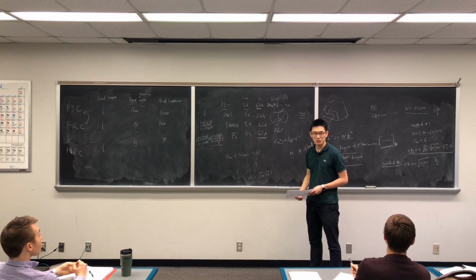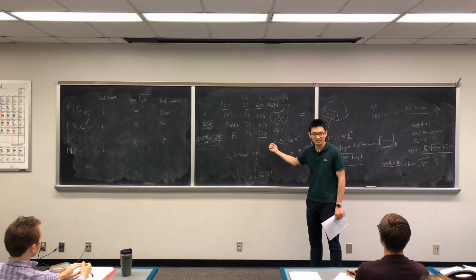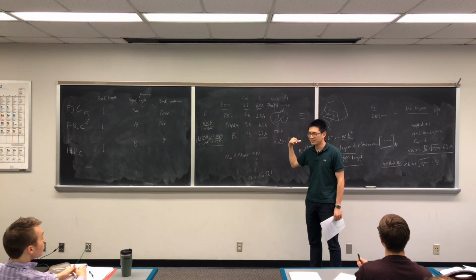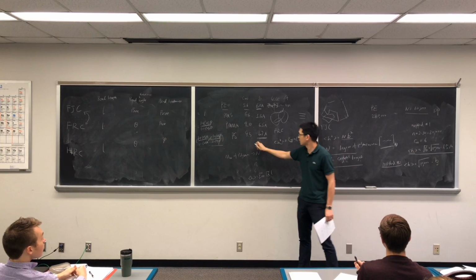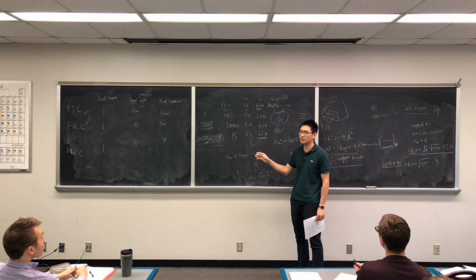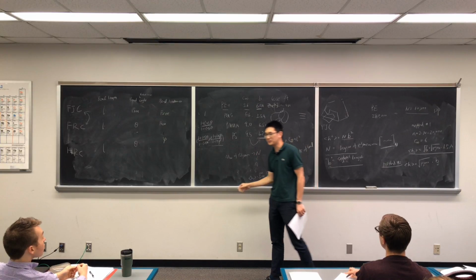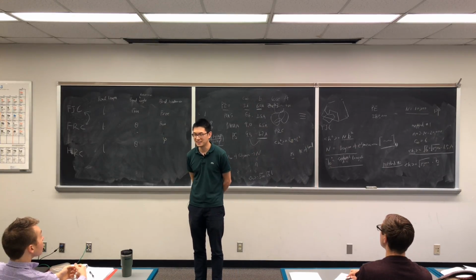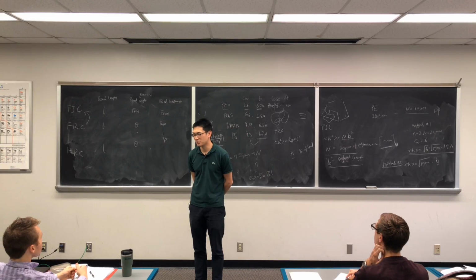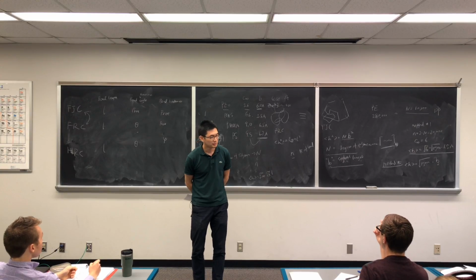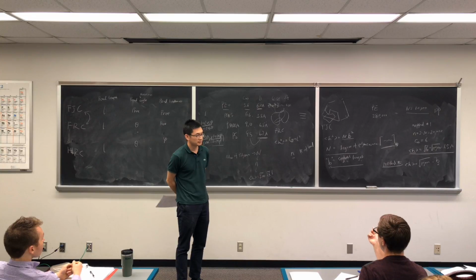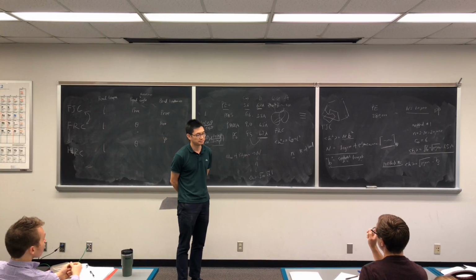So the beauty of this is you don't need to consider bond angle. The characteristic ratio has been rolled into this term. All you need is to calculate the degree of polymerization n, and you can use NB squared to understand that. So you can just look up N and B and the C infinity term for any polymer.